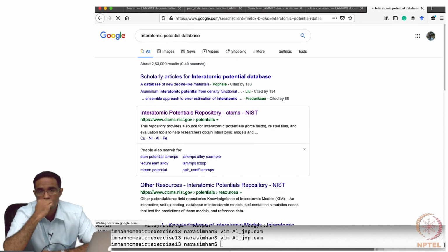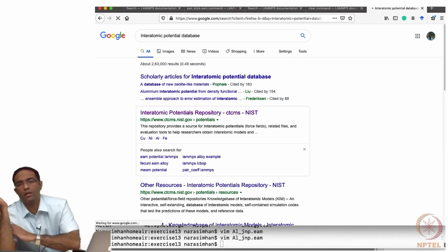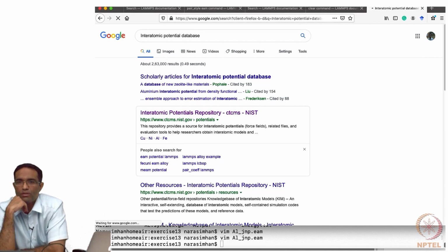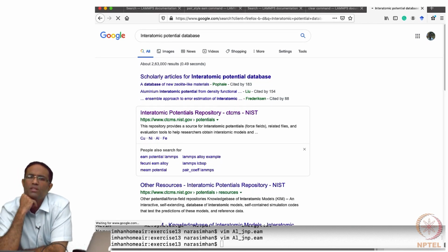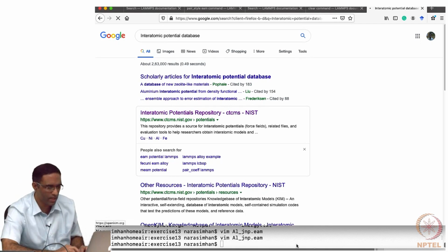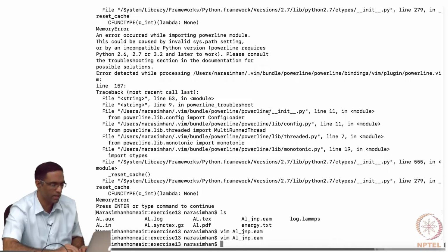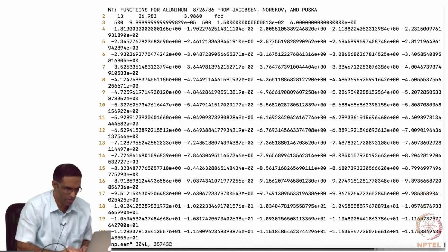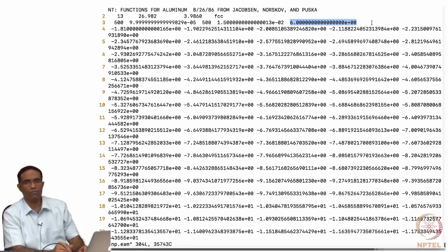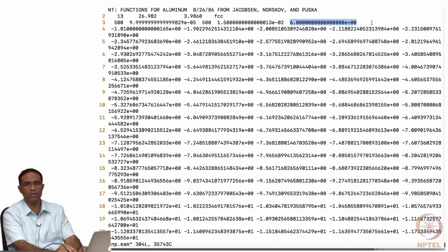And in case of Lennard-Jones, we were writing pair style lj/cut and the cutoff length. Correct, epsilon, sigma and then the corresponding cutoff radius. Yeah. So in case of EAM, we don't need any cutoff distance or anything. It's there actually, in the file. You don't have to explicitly specify it. This is the cutoff. So we don't have to specify it in pair style for the EAM potential.